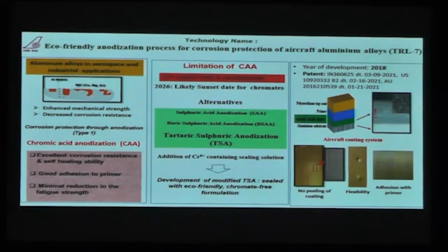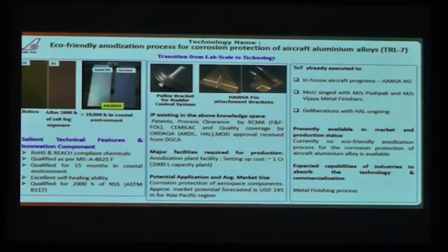You can see that it adheres very well to the primer, and the flexibility is very intact. There is no peeling of the coating when you drop a kg ball on top of it. And the adhesion with the primer on the right side is very much intact. Foremost, it is totally free from any hazardous chemicals, and is totally RoHS and REACH compliant.